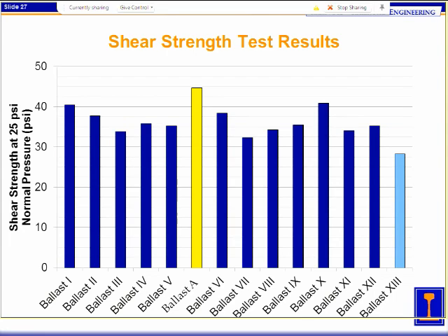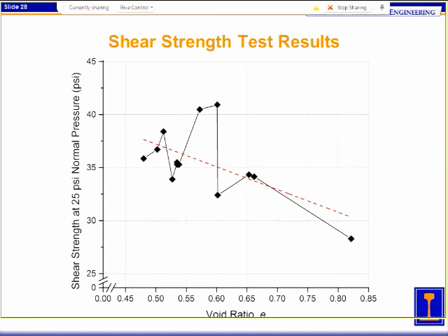So as we stated at the beginning, Union Pacific had observed this in track, actually, pretty high variation in their ballast materials. So one area where we found some good correlation, or somewhat decent correlation relative to everything else we looked for correlations in, was with the void ratio, actually. In general, there was a decreasing trend between it and shear strength, but as you can see, not a great trend, still kind of bouncing all over the place.